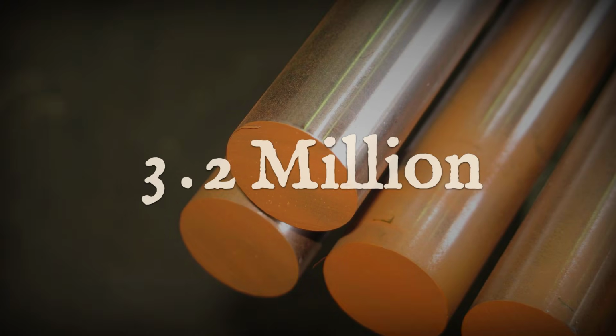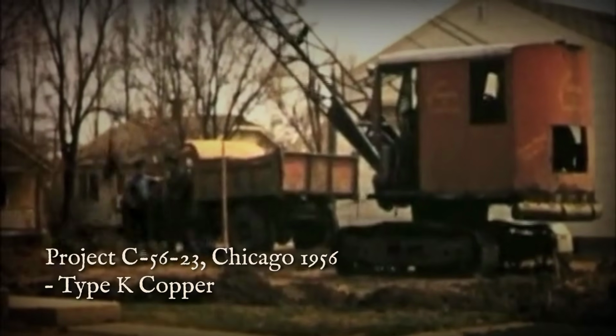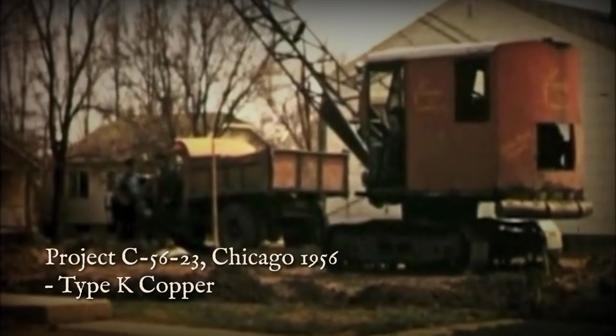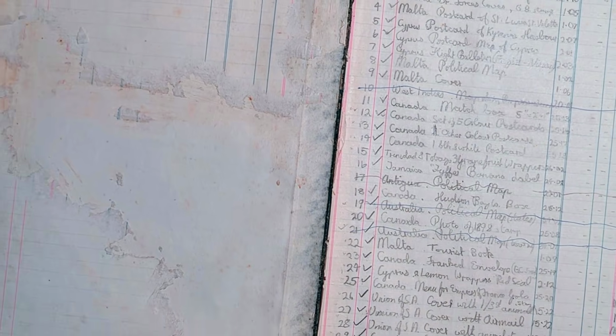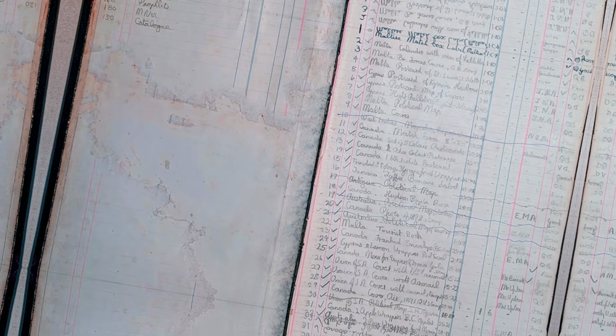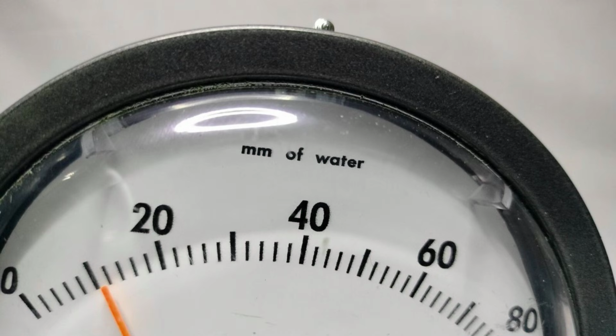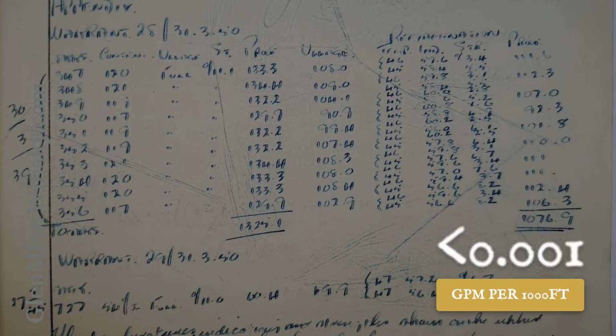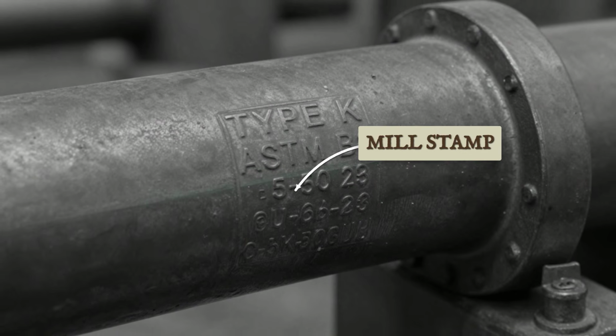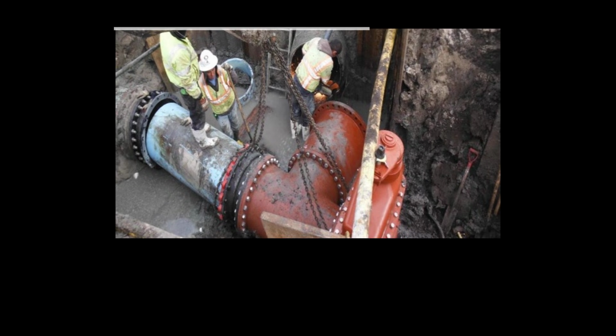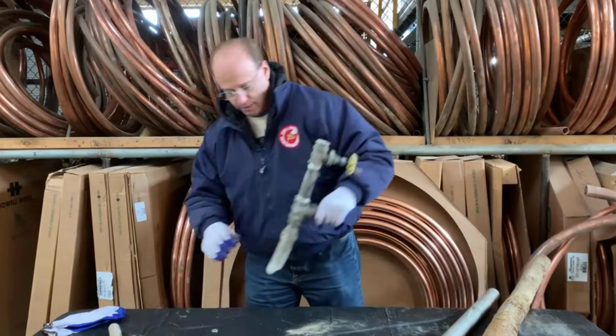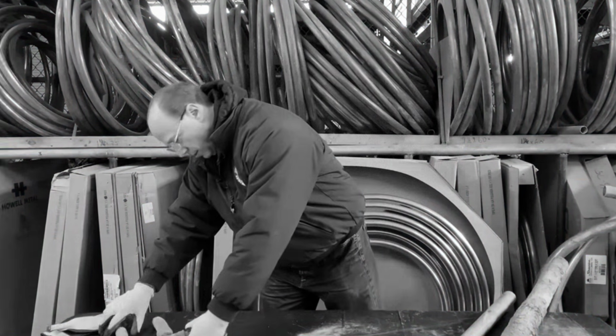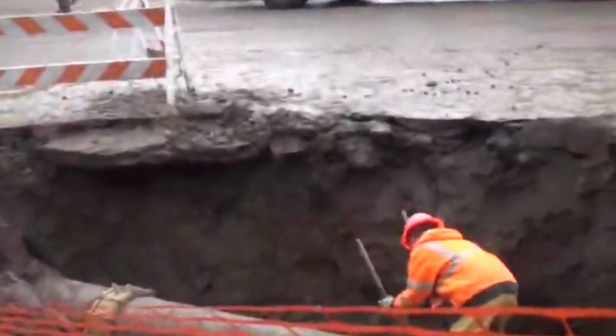Municipal records from mid-century Chicago tell the story in numbers that still stagger the imagination. 3.2 million feet of Type K copper, specified for Project C-5623, were laid beneath the city streets in the 1950s. Daily logs from foreman Joe Malloy, his handwriting still legible in the archives, record leak rates so low they barely register, less than 0.001 gallons per minute per 1,000 feet. The pipe was not just installed, it was measured, tested, and stamped with mill certifications, each length traceable from foundry to trench. Maintenance records decades later confirm the promise. The copper mains remain in service, outlasting the engineers who signed off on their installation.